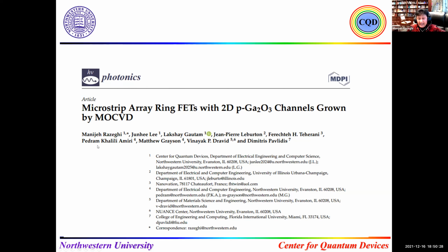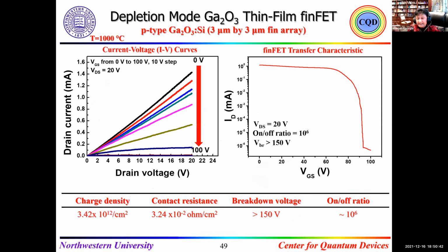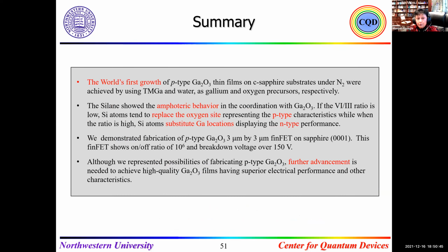Professor Khalili did further characterization to demonstrate that it is p-type, and this paper, as you can see, just came out yesterday, and this shows the result that yes, we can do p-type, but how - by doing the 6-to-3 ratio again with doping with silicon, using nitrogen as the carrier gas at high temperature to maintain the alpha phase, and at the same time making a very thin layer, only about 100 nanometers, which is one of the beauties of the system.